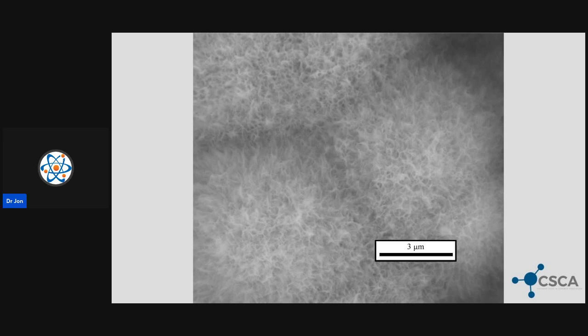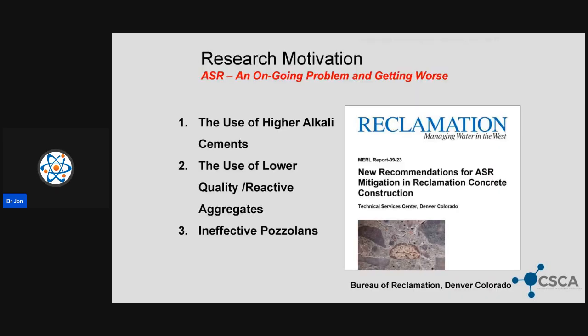And if you've never read her paper, Kim Kurtis, back in 1996, and I brag about this paper way too much, did a paper on soft X-ray spectroscopy, microscopy. I can't remember the last word that she used, but basically what she was looking at is this fibrous morphology of the ASR gel rosette. Why that's important is because we have these needle-like fibers or fibrils that are crossing over each other, creating pores that have extremely large and then small diameters all the way through. What that does is it creates a capillary suction that draws in not only the pore water solution, but the salts, which will induce more expansion.